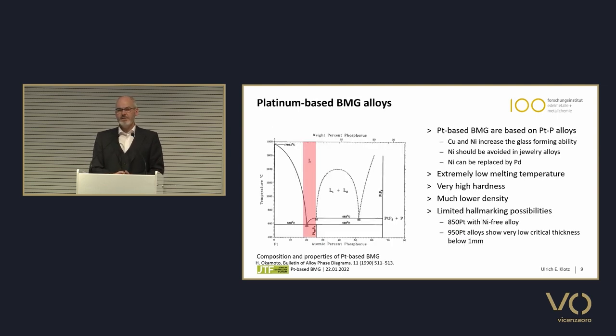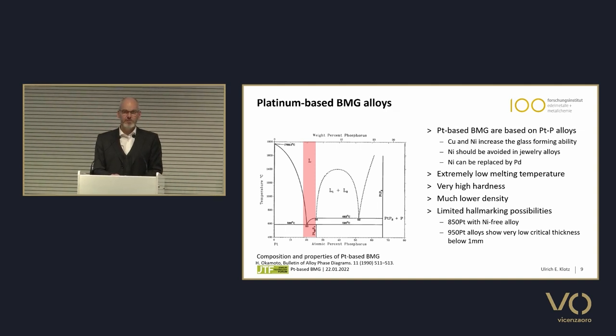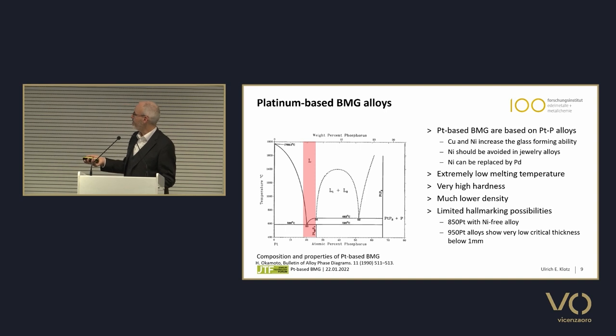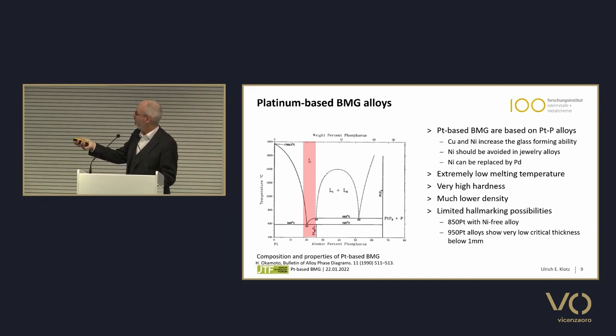So let's have a look at the platinum-based alloys we worked with. We were focusing on platinum-based bulk metallic glasses that are based on platinum-phosphorus alloys. And this is a phase diagram of platinum and phosphorus. And I told you about the dramatic reduction of the liquidus temperature, which this line here is the liquidus line. And there is this eutectic composition, and the red area marks the interesting composition range of these alloys.